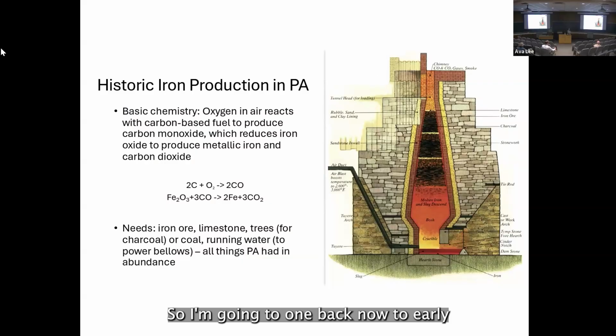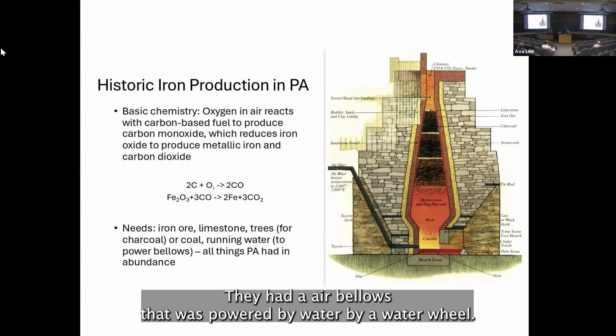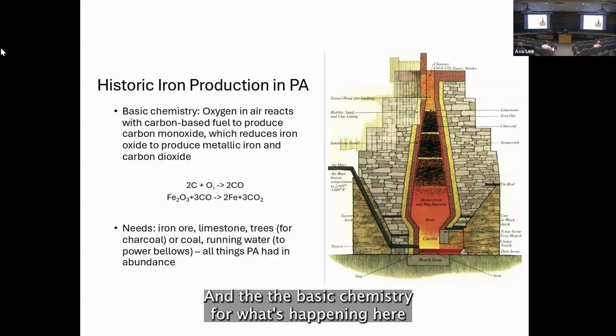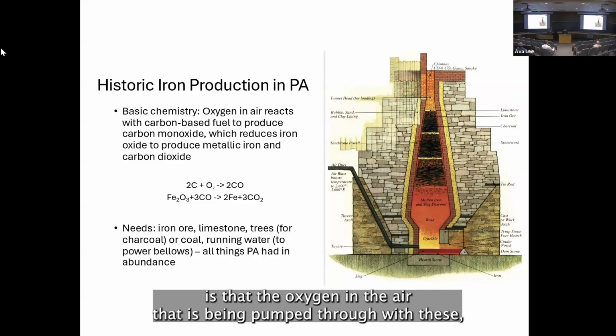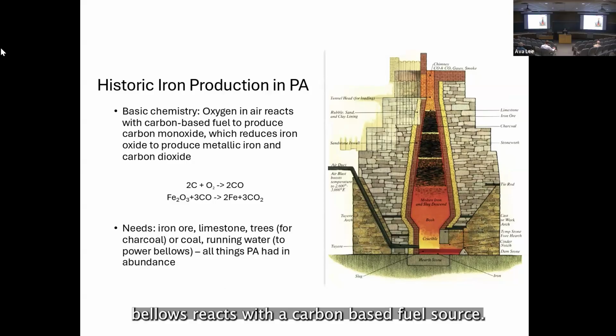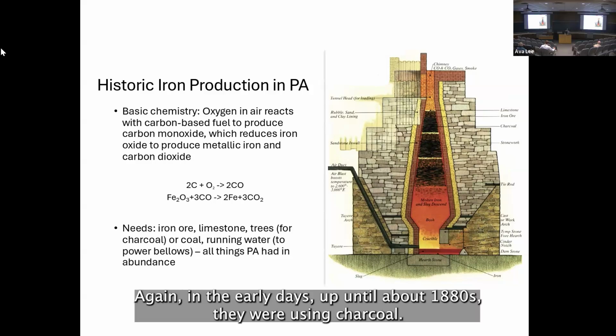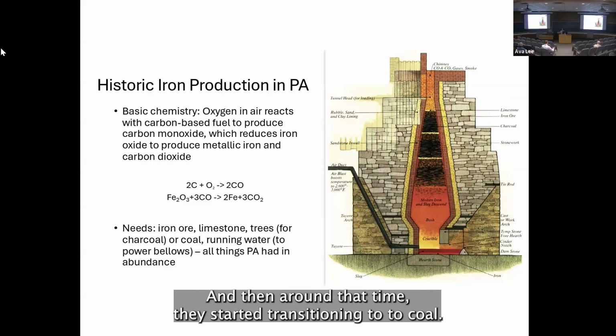So I'm going to wind back now to early 18th century, mid 18th century. Iron production is taking off, starts in the southeastern part of the state in what's called a cold blast furnace. These furnaces were fired by charcoal. They had an air bellows that was powered by a water wheel. And the basic chemistry for what's happening here is that the oxygen in the air that is being pumped through with these bellows reacts with a carbon-based fuel source. Again, in the early days up until about the 1880s, they were using charcoal, and then around that time they started transitioning to coal,